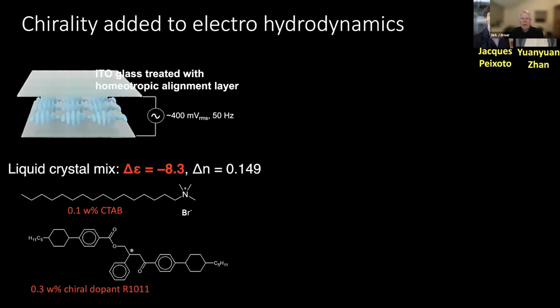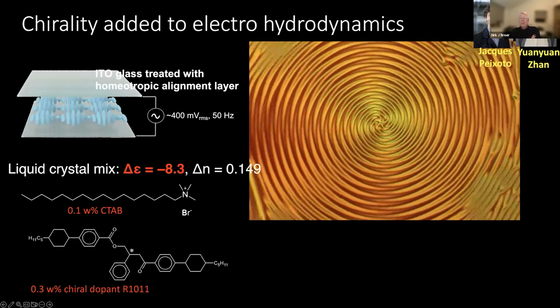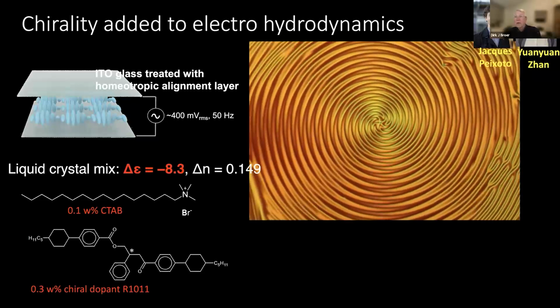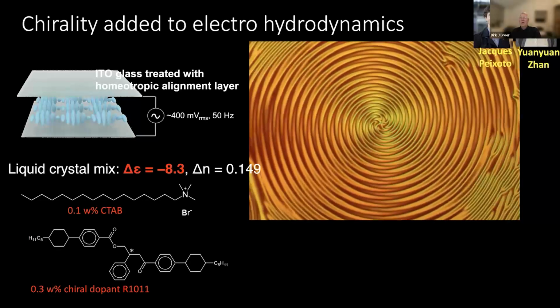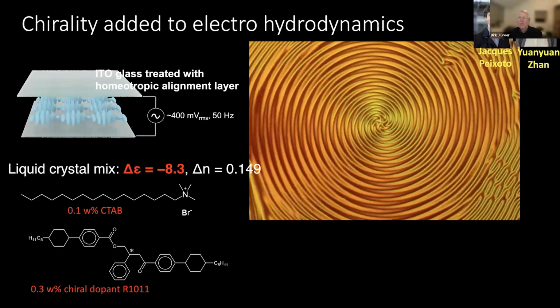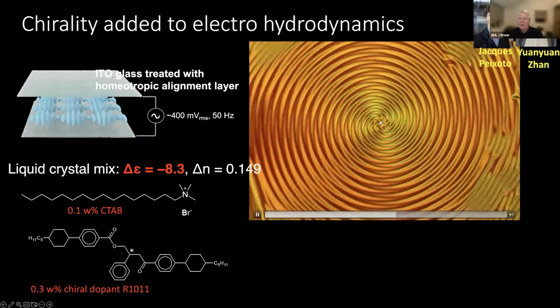One step further with this, if you add chirality to this system, and this is work that was done by Yang and Chuck in our group. If you add chirality to the system, here again, we have the ionic compound. This can be this surfactant molecule, but it can again be the spiropyran molecule. Then if you start addressing this effect, then you can convert the electrohydrodynamic motions into this very well-controlled circular motion around a defect structure, as you can see here.